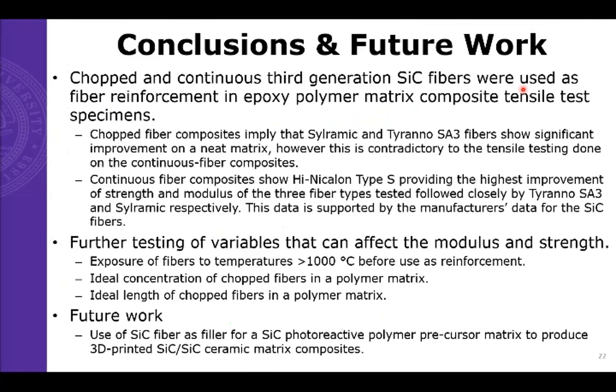So to conclude, our chopped fiber composites seem to imply that Sylramic and Tyranno SA3 fibers show significant improvement over the neat matrix. However, this is contradictory to our other tests, such as the continuous fiber composites, where Hi-Nicalon Type S provided the highest improvement of strength and modulus of the 3 fiber types, followed closely behind by the Tyranno SA3 and Sylramic respectively. And this data is supported by the manufacturer's data for the silicon carbide fibers and our other testing through other methods.